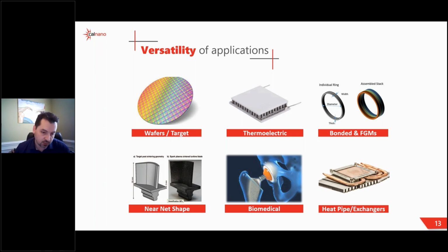Another area that's showing a lot of interest recently is net shape manufacturing. With SPS, we're not limited to just doing what's possible with the tooling. With some other technologies, in this case a binder jet, which I'll cover a little bit more of, we will 3D print, binder jetting one material with a cocoon around it, essentially. That cocooned powder compact is then placed inside of a die with a space filler support powder, and then that is SPS'd. At the end of the day, the support powder is removed, and you're left with a complex geometry part that has the enhanced benefits of SPS in a fully consolidated 3D shape.